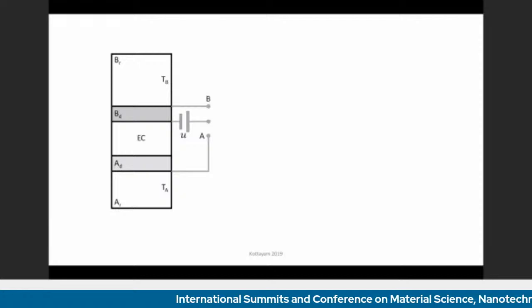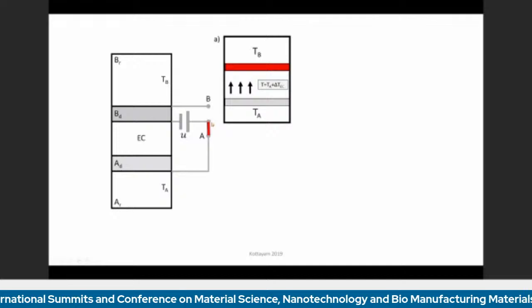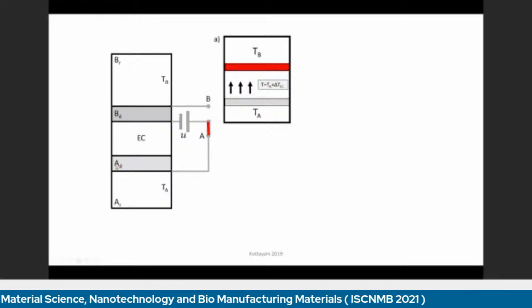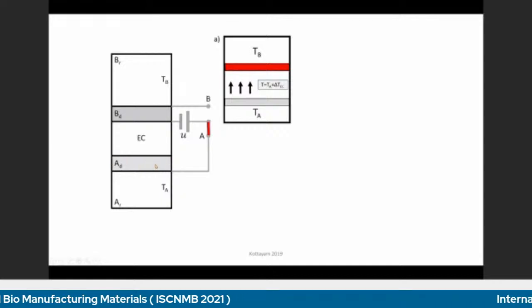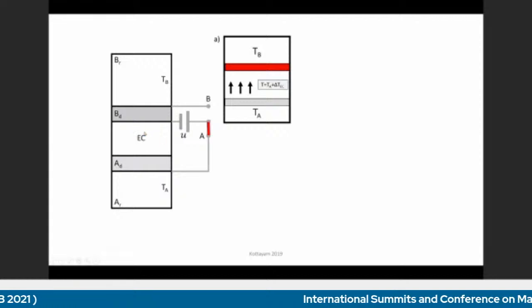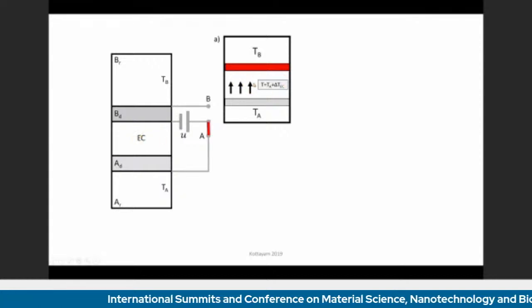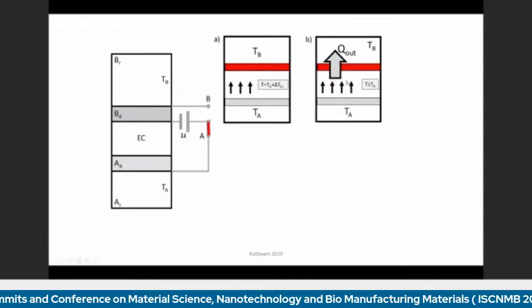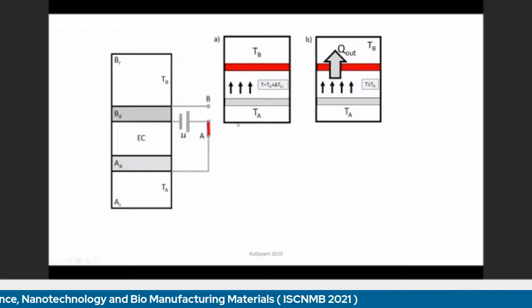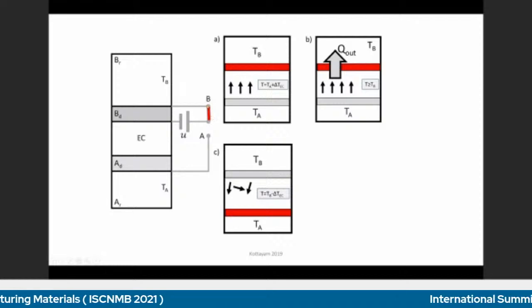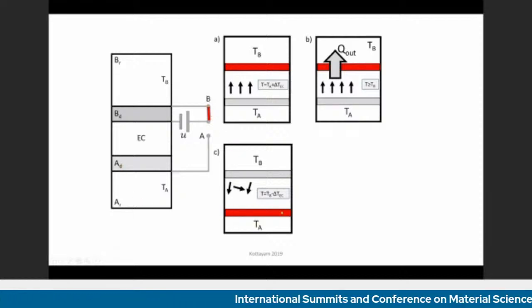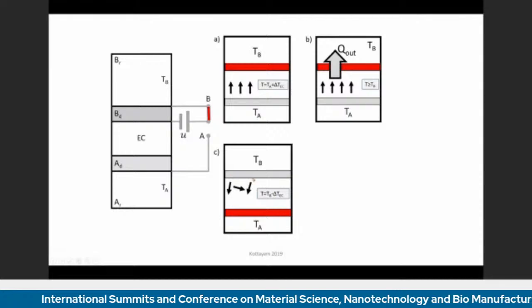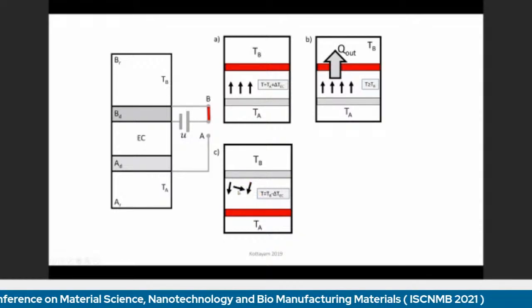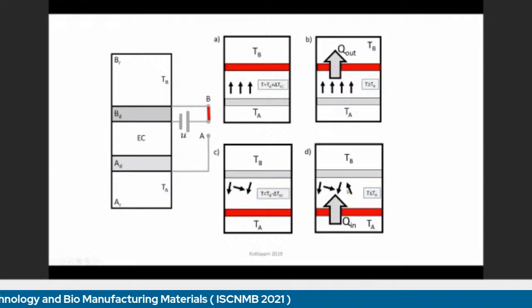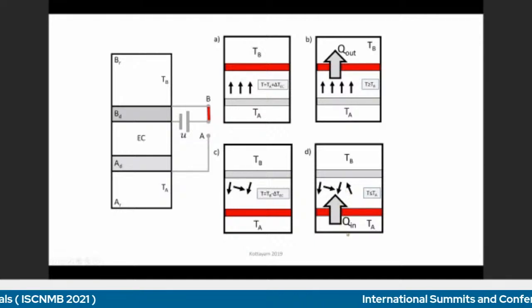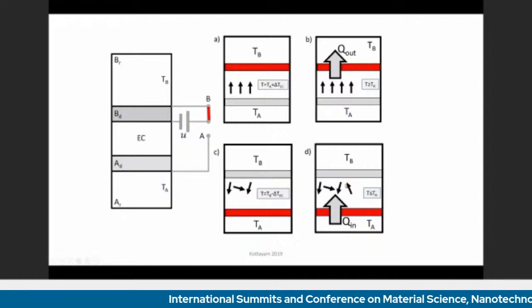So when we apply an electrical field, what happens? If we switch this connection, we actually make this diode become an isolator, and because the liquid crystal is in an electrical field, it aligns and heats up. Because it heats up, this heat can be transferred to the top. And when we switch the electrical connector to B, this means that the diode at the bottom becomes an insulator, the diode at the top becomes a conductor, the liquid crystal becomes disoriented, and later on, because of the decreased temperature, it draws heat from the bottom, so that we get a very efficient refrigerator.